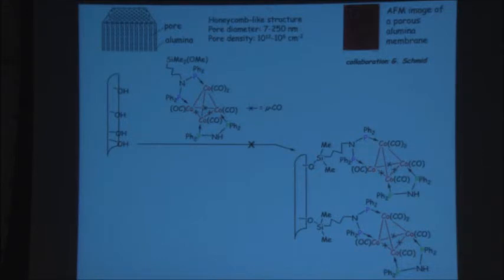So we applied that now to the cobalt system. We've tried first to react the functionalized cobalt-4 cluster with the tail here with the OH group on the surface, but that did not work.